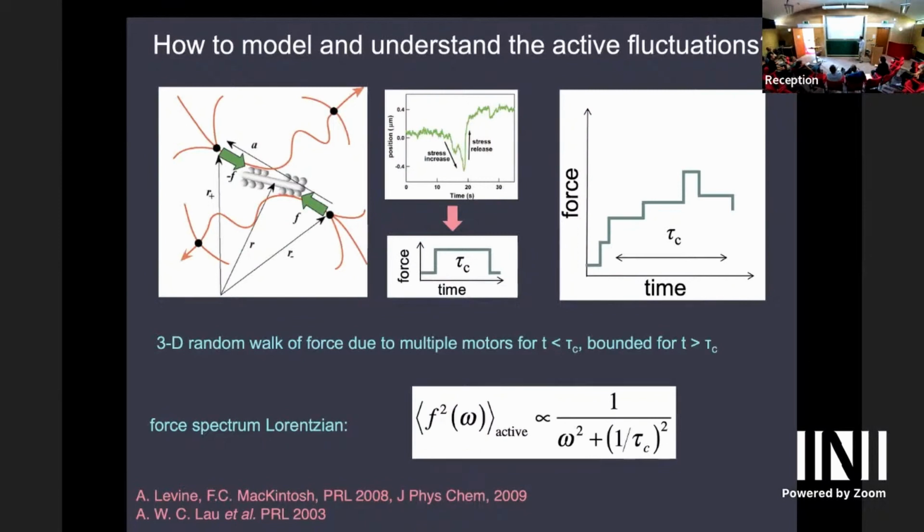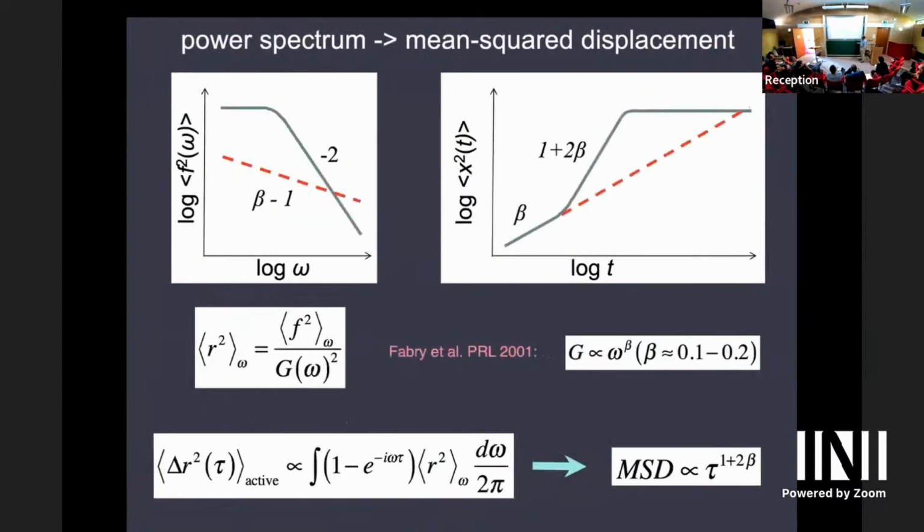So this is the force spectrum. What is the surroundings in cells? Well, that's fairly well studied. Ben Fabry in Jeff Fredberg's lab, for example, way back, did a lot of experiments, and it's pretty well established that cells act like rubber balls at intermediate frequencies. At very low frequencies, they can flow and adapt. At high frequencies, they have viscoelasticity that goes up with some power law, but at low frequencies, and we're talking about 0.1 to 10 hertz or so, they have what's called weak power law or elastic plateau behavior, soft glassy rheology.